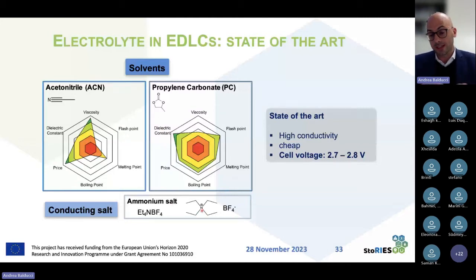Because their size is not too big. And what is also very important is that the mobility of the cation and the anion is rather comparable. Because, of course, the mobility in this system should be as symmetric as possible, because we don't want to have an electrode which is much slower or which is not able to store as much energy as the other, because this will then make the performance of the system not as good as we wish.